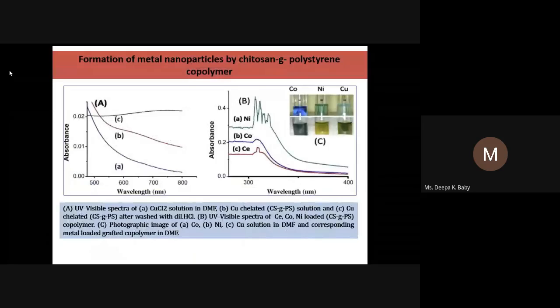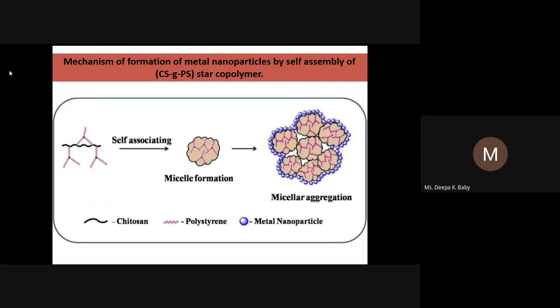Then this compound can be used for the generation of nanometals. Nanometals can be generated from this chitosan polystyrene copolymer. And when chitosan polystyrene is incorporated with nanoparticles, since chitosan itself has antimicrobial property, if you are using metal nanoparticles in it, the property can be enhanced. So it is a very good material for wound dressing.